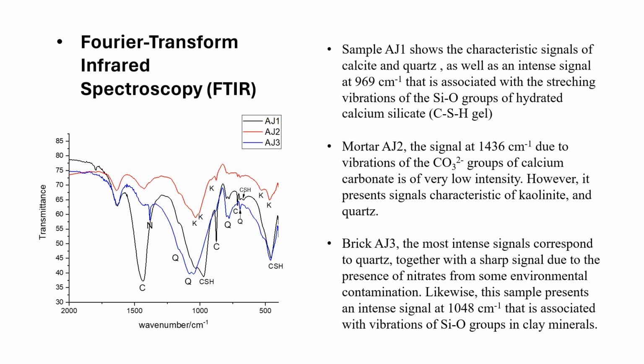The FTIR shows that sample AJ1 shows the characteristic signals of calcite and quartz, as well as an intense signal at 969 centimeters -1 that is associated with the stretching vibrations of the SiO groups of hydrated calcium silicates, CSH gel.